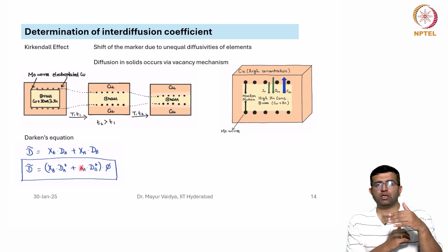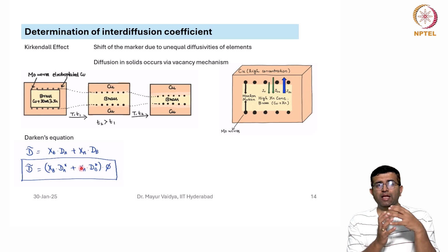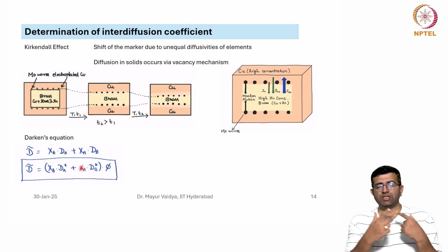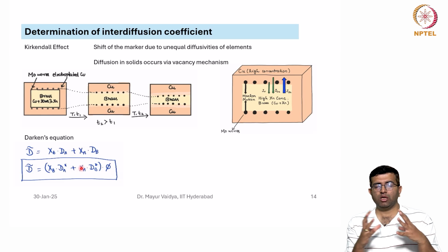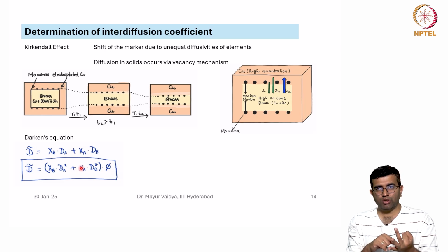It is slightly different from the self diffusion coefficient, where there is no driving force present. It is different from the interdiffusion coefficient, which talks only about the intermixing of A and B. So we also need to remember the difference between the tracer diffusion coefficient, self diffusion coefficient, intrinsic diffusion coefficient, and interdiffusion coefficient.